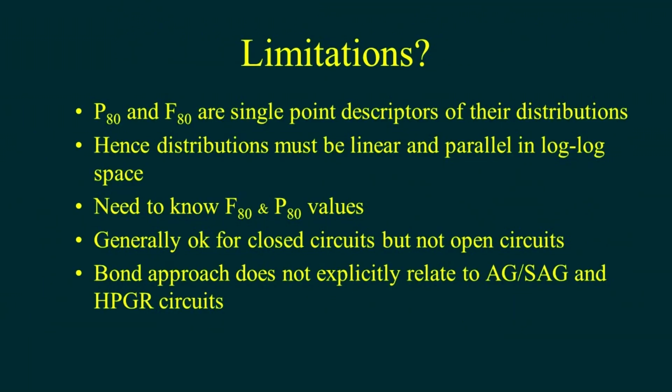All right, what are the limitations of these power-based equations? Well, the first one is that because we're using single point descriptors, P80 and F80 are used to describe an entire distribution. For the maths rules to be correct, those distributions must be linear and parallel in log-log space. If the rules are not obeyed, then you cannot use those power-based equations. If you do, you will get the wrong answer.